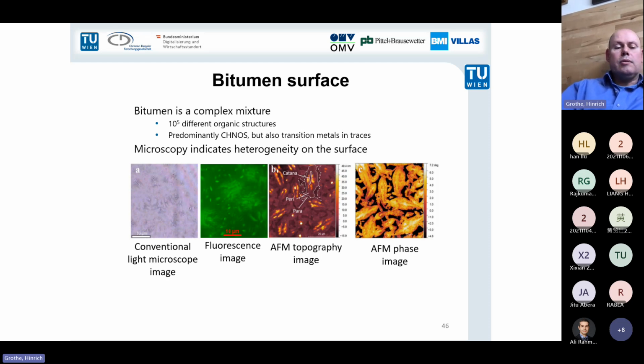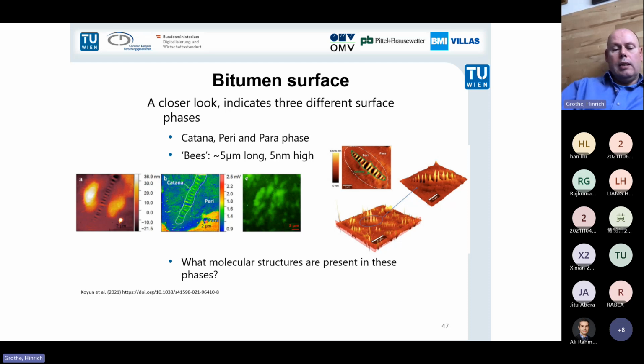And then on the left-hand side, you just see conventional microscopy. And so we can characterize our system. We see that these so-called bees are about 4 to 5 micrometers long, and they have a height of up to 5 nanometers. And there's a chemical difference. So it's not a homogeneous chemistry in that surface, but the structure has a different chemistry if you go from the inside to the outside, and the matrix is also chemically different.